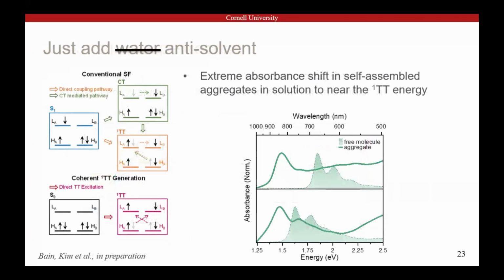But fortunately, my postdoc was undaunted and found one more trick up his sleeve, which was to induce an aggregation with anti-solvents. In this case, it turns out that these molecules really hate chlorobenzene, and that makes them pack together like nothing else. So when we dissolve these molecules in chlorobenzene, we get this absolutely gigantic shift in the steady state absorption, 350 millielectron volts. And this is totally reversible. If we put good solvent back in, it hops right back to this unaggregated free molecule position. But this degree of shift is by far the strongest interaction between pentacenes that has ever been reported anywhere. So this is really a gigantic coupling that we're turning on in the monomer and in this dimer.